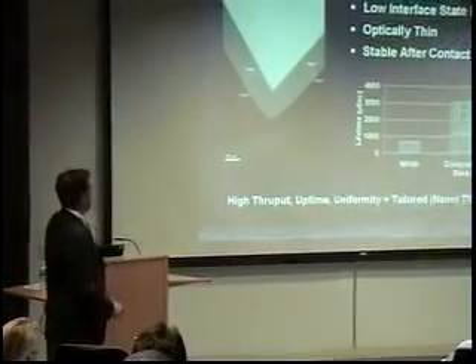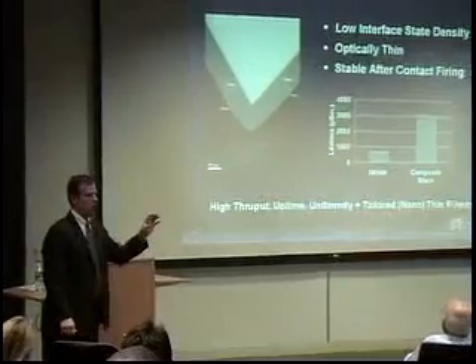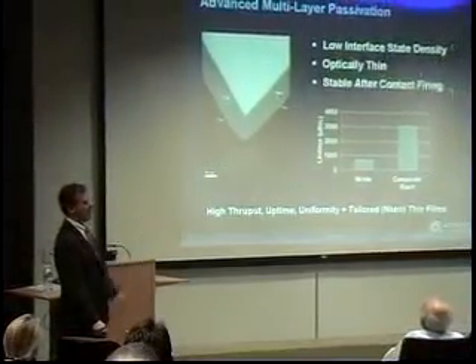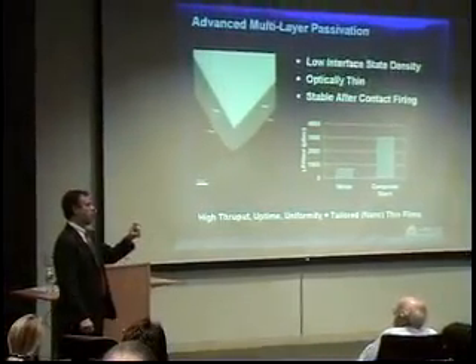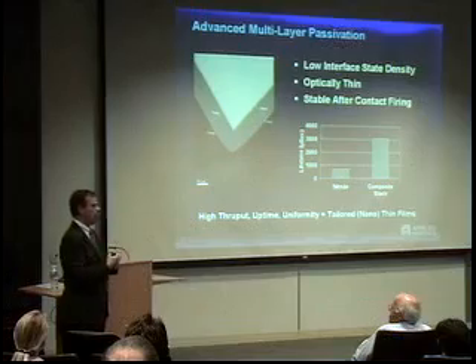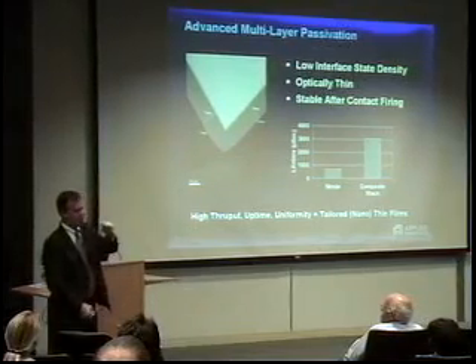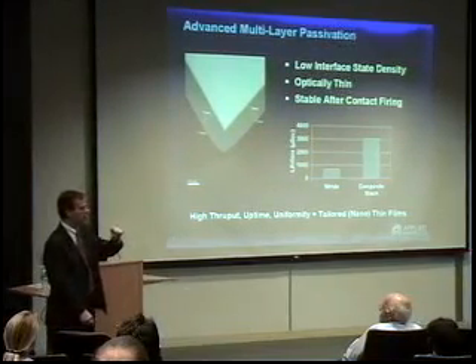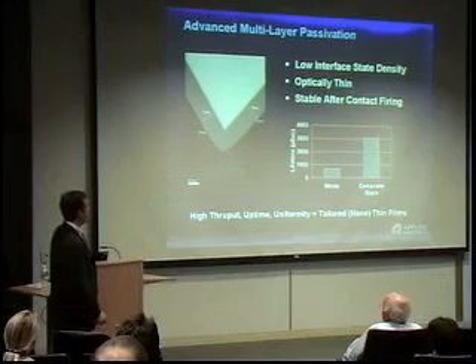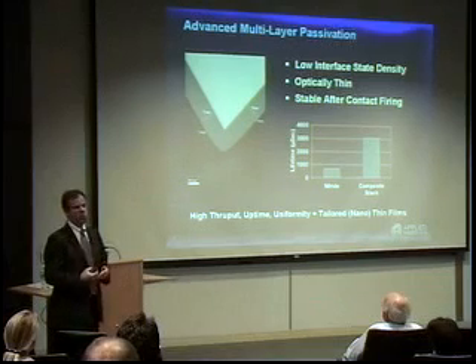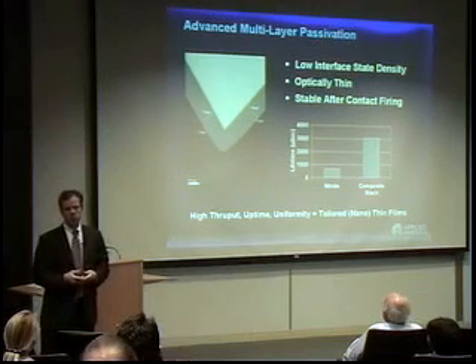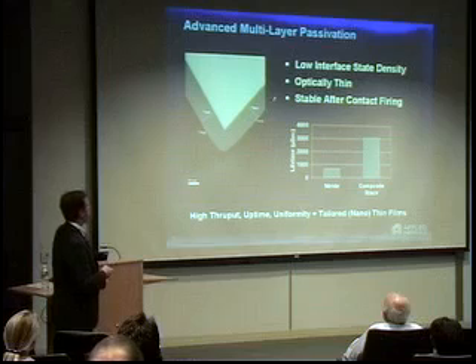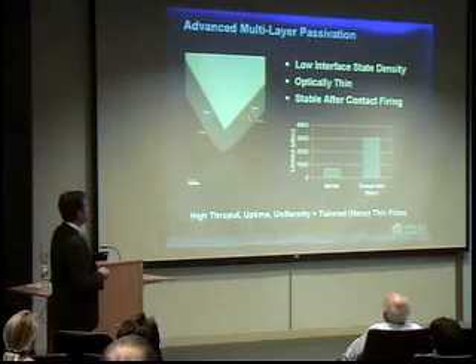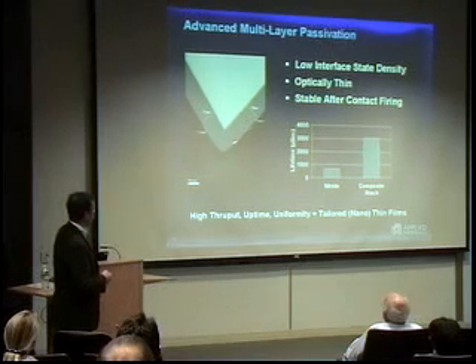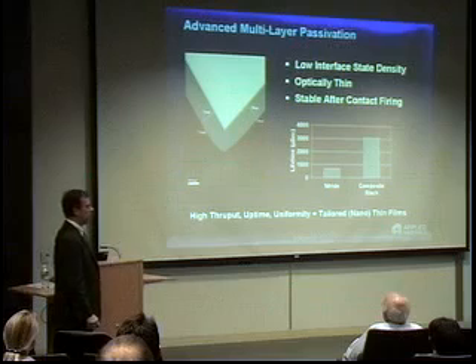So how about some other things we're doing? So I showed you earlier this cartoon with this one layer of anti-reflective coating, but it actually did two functions. It sucked in the light, an optical function, and the other function was it passivated the surface so we didn't lose electrons and holes. Those are two separate functions that really require two different materials. So one way to do that is to use a stack of materials, the top one to get the light in, the bottom one to get the passivation.